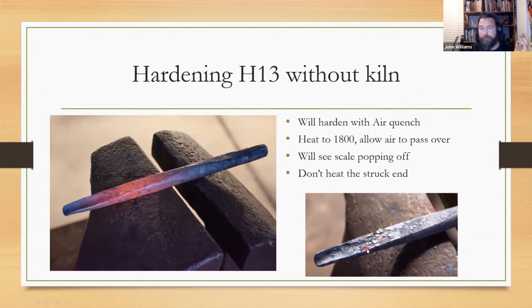But if you don't bring it up to critical temperature and it doesn't have the scale pop off, remember the color that you did, and don't take it all the way up to what you think is 1800 and then just try to guess at it. Get it a little bit hotter, like a shade hotter than what you would do for normal steel, and then let it air harden. If you see that scale pop off, test it with a file, see if it's hard. And then if it's not, put it back in the forge. It won't hurt it.